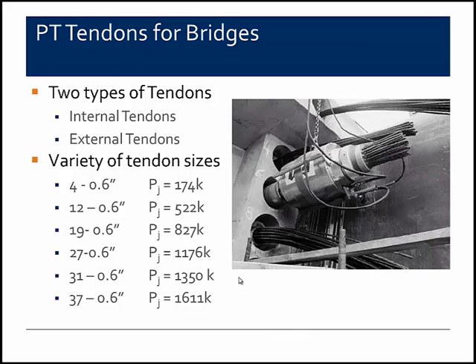I mentioned earlier that my background is in bridge construction, and there are really 2 types of tendons used in the large bridge structures. There's internal and external tendons, and we'll discuss what those are in a slide or 2. I've also shown here the variety of tendon sizes that are primarily used on bridge structures, and you can see also the jacking force used for those tendons, and we're dealing with extremely large forces. That 37 strand 0.6-inch diameter tendon at the very bottom, that's a jacking force of 1.6 million pounds. So there's a tremendous force in these tendons to hold up these bridge structures.